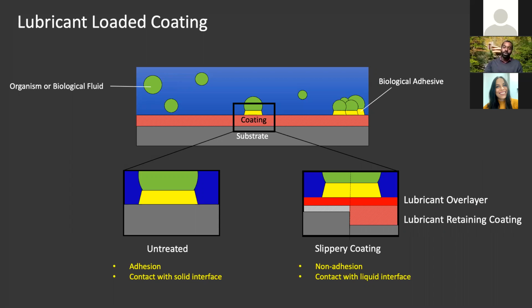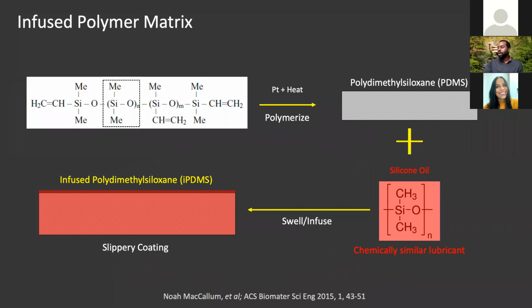One way may be to have the lubricant penetrate completely into the coating, and not have a thicker coating, not just a thin little film. And we might be able to do this by infusing this lubricant, this liquid, into a similar polymer system. So to have this matrix, and then to have this liquid that impregnates the matrix and then presents at the surface. We have shown this through using PDMS, so using these silicone systems where we polymerize them to form the actual polymer network. Then we add in the oil, which then intercalates into the polymer network. So we call it swelling or infusing.